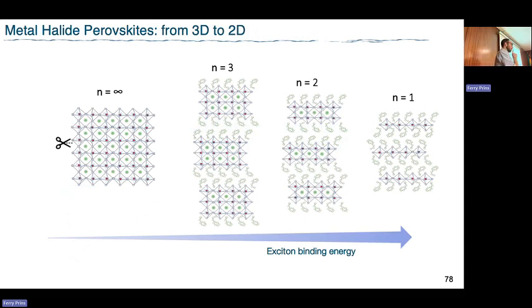So 2D systems, two-dimensionals, but this is also perovskite. This is your bulk perovskite. And you just do your synthesis without any organic long ligands, you just get an infinite system of corner sharing octahedra. Then you introduce long cations, which act as scissors. And the ratio between these longer cations and your original precursors allows you to control the thickness of your inorganic layers. Now you have a two-dimensional layer that can either contain, for example, 3 octahedra of lead iodide, lead bromide, or 2, or 1. I'm going to focus on this one.